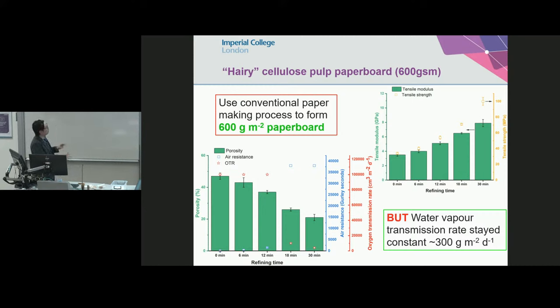A lot of information to digest, but let's look at the bottom left-hand side corner here. The more you refine, the lower the porosity of this material, because the free flowing fibers, the hairiness of the fibers, start to pack in between the gaps formed by the larger fibers, reducing porosity. So that's great. Once your porosity gets reduced, your air resistance, or these blue squares, suddenly jumps up. And this is actually a lower bound, by the way. Our instrument couldn't go any larger than 38,000 seconds. So this blue curve, the higher the value, the better. That pore blocking effect actually helps increase air resistance.